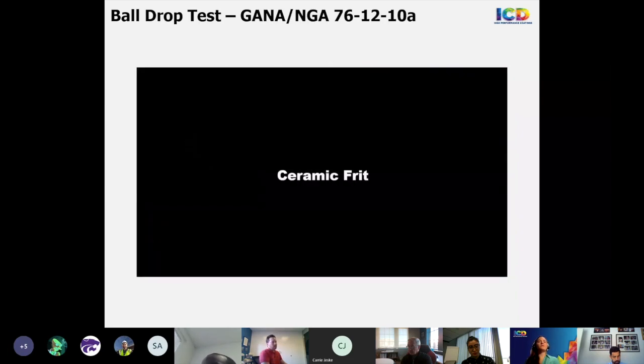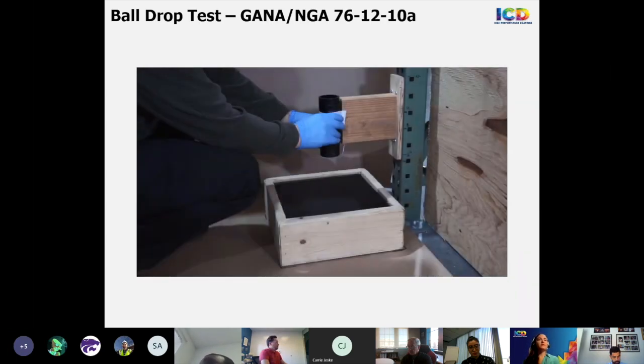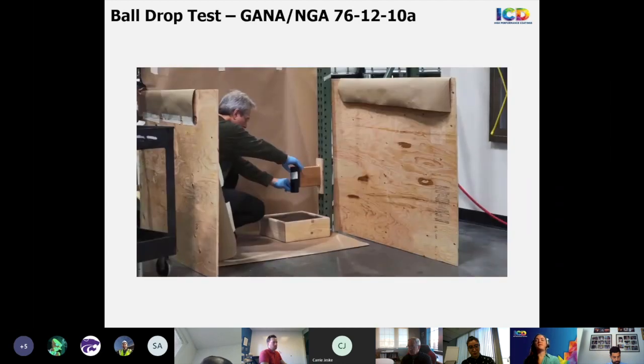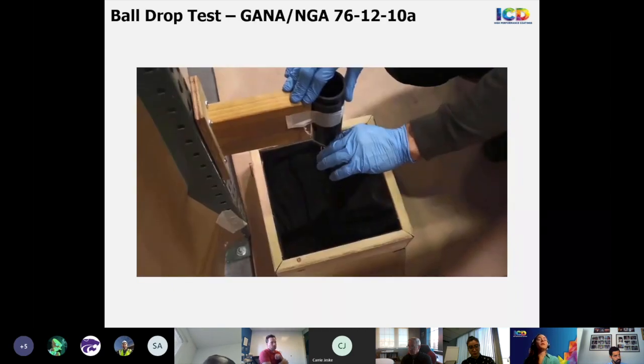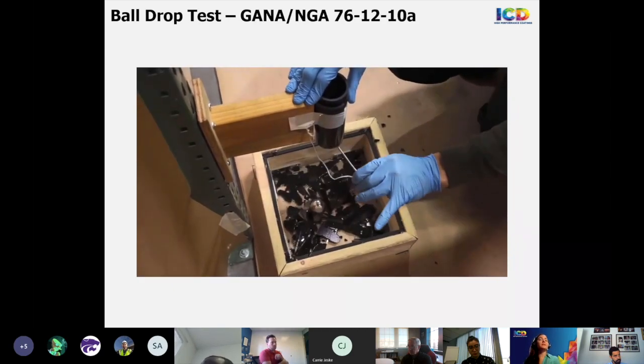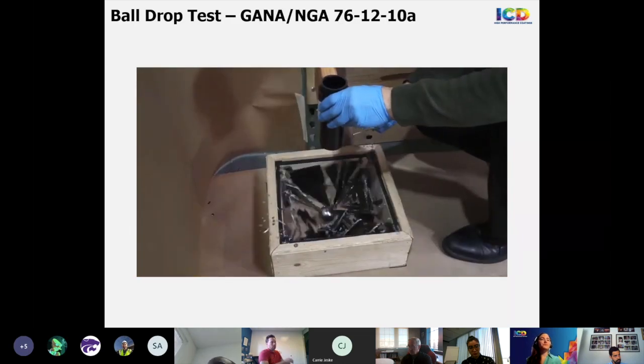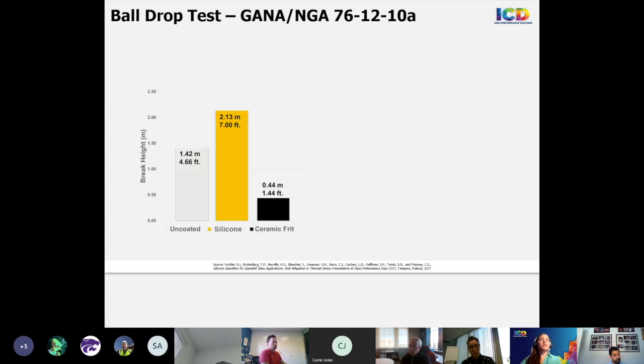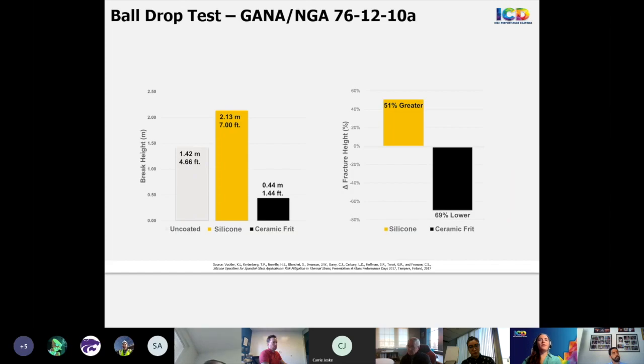And now we have the results for ceramic fritted glass. And the glass breaks at a very low height. So the ball drop experiments in this video support the fact that silicone coatings do not weaken the impact resistance of fully tempered glass while ceramic Frit can. So here's just a comparison of these results in graph form. And on the right, we're looking at the conditions of just the two coatings and comparing changes in terms of percentage. There's a 51% increase with silicone and decrease of 69% for a Frit.